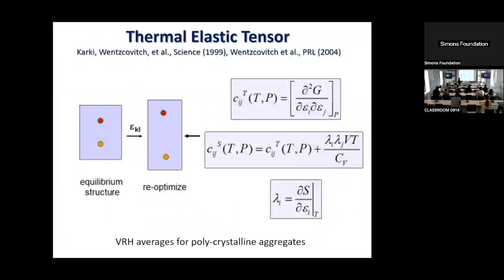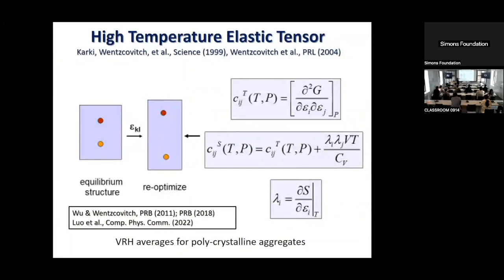We needed the adiabatic elastic coefficients, and there's another correction there. As you can see, this is the high throughput nature of the calculation that we started doing in the late 90s. Today, it has been facilitated greatly by semi-analytical expressions for this quantity. Essentially, we need mode Gruneisen parameters and strain Gruneisen parameters in order to carry out these calculations more efficiently today.